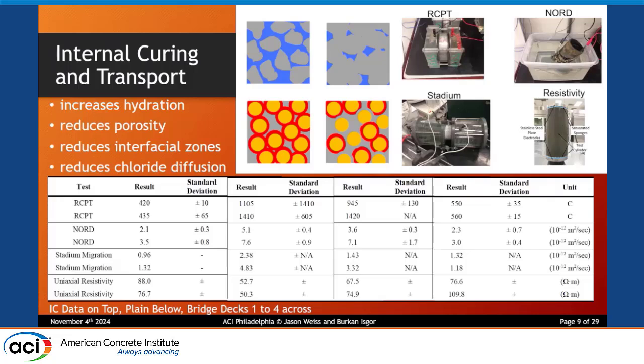Now, earlier this morning, there were a lot of questions on what's the best test to use to measure your transport properties. They all give you similar results. All right? If you like the RCPT test, if you like the NORD test, if you like the stadium test, you want to do resistivity, you want to do something else, they can all be correlated back to each other, and then they can be used in service life models. The big takeaway from this, though, is we've heard about internal curing is going to increase the reaction of the cement, the SCM, the biochar, the fly ash, whatever else is in the system. It's going to increase that reaction. By increasing that reaction, you reduce the porosity of the system.